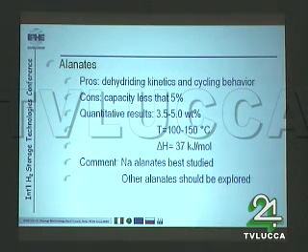The quantitative results obtained up to now are for storage capacity from 3.5 to 5 weight% at temperatures between 100 and 150 degrees centigrade with enthalpies of about 37 kilojoule per mole. The comment is sodium alanates are best and most studied. Other alanates should be explored.